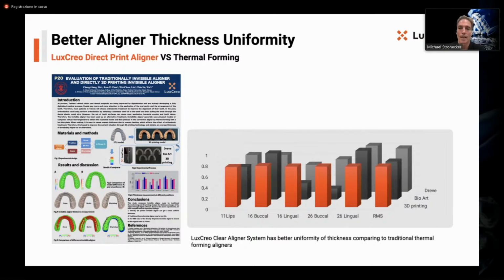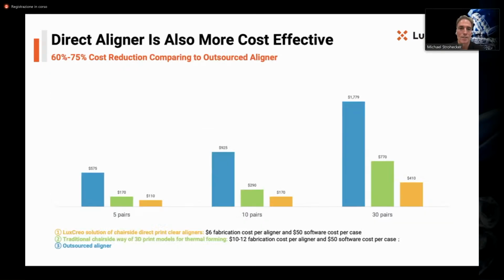Now, when you look at other methods of printing, where you do the dental model and the thermoform, you see that there's thinning. It's a stretching of the material. And so the forces that you want to apply are weaker in those areas and can limit the addressable stages and cases. And it leads again to more revisions.